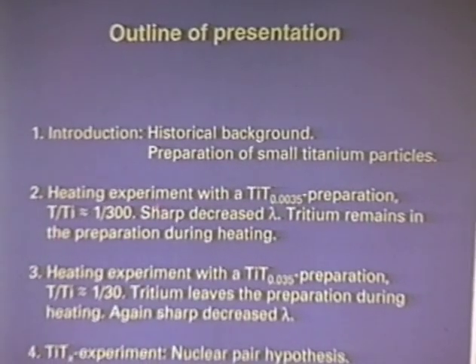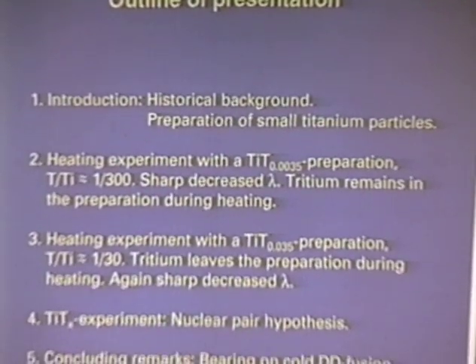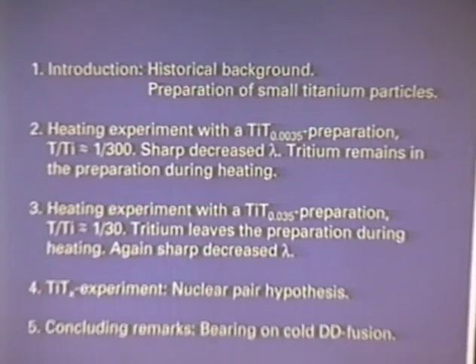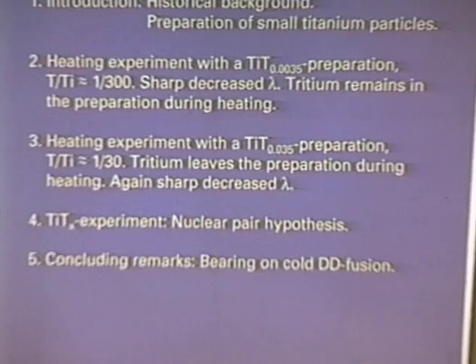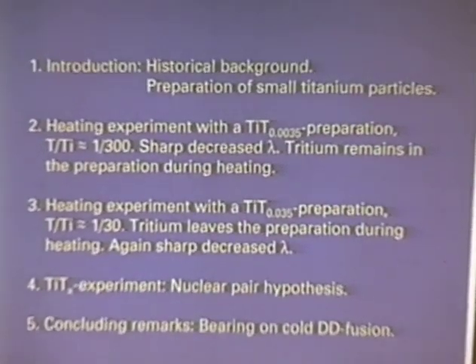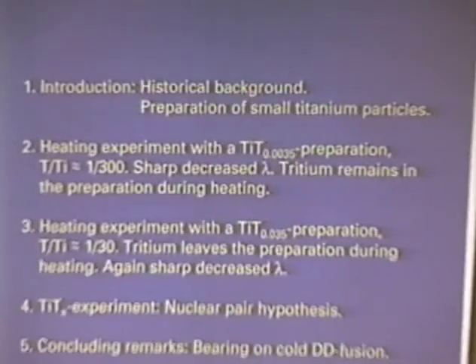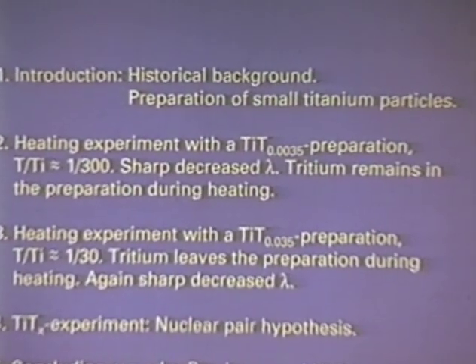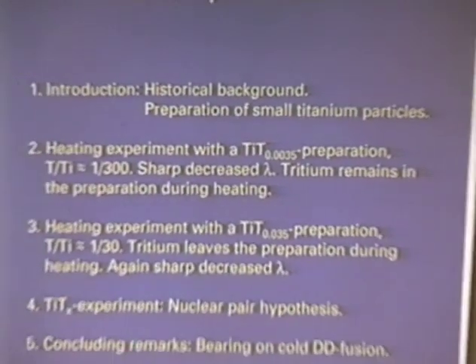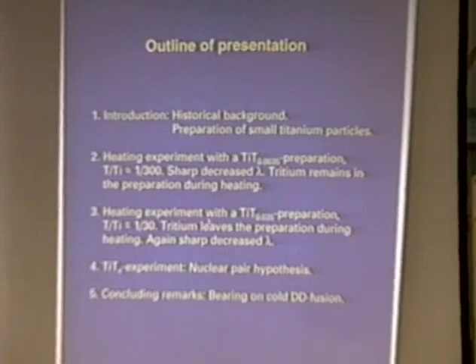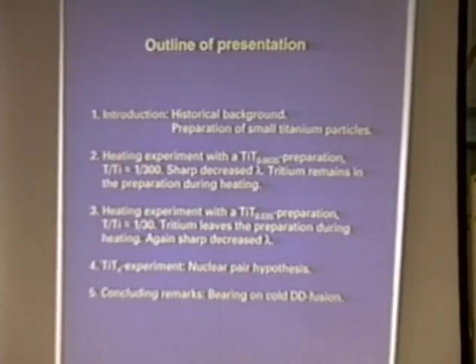With this experiment, during the whole increase of temperature, the tritium remains in the preparation. And we observe a sharp decrease of the radioactive decay constant of tritium. In this experiment, the tritium leaves the preparation during heating, but again, a sharp decrease of the radioactivity is observed.